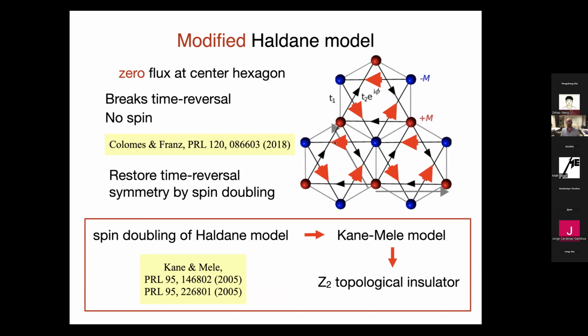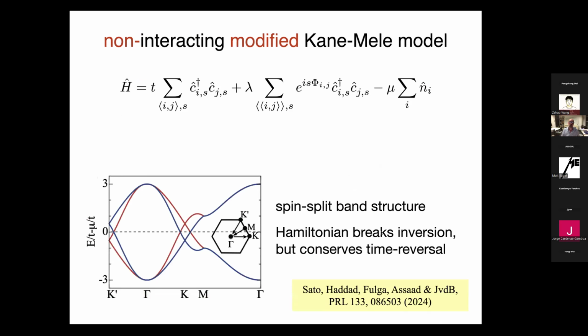What we did now was take this modified Haldane model and restore time reversal symmetry by spin doubling. If you do this for the regular Haldane model, you get the Kane-Mele model. And the Kane-Mele model is famous because it is the model that showed that there is a Z2 topological insulator. So we consider a modified Kane-Mele model. And the Hamiltonian is here. It has nearest neighbor hopping, and this term encodes the next nearest neighbor hopping, which is imaginary and reflects the presence of these fluxes.